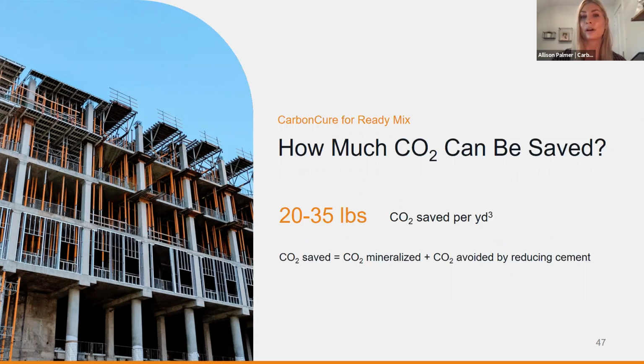But the majority of the carbon savings come from the ability to reduce the cement content. When we're reducing cement by about 5 to 6%, we're reducing about 20 to 40 pounds of material. Those savings can really add up on any given project. If you're doing any sort of back-of-the-napkin math, a safe figure to use would be 25 pounds per cubic yard.